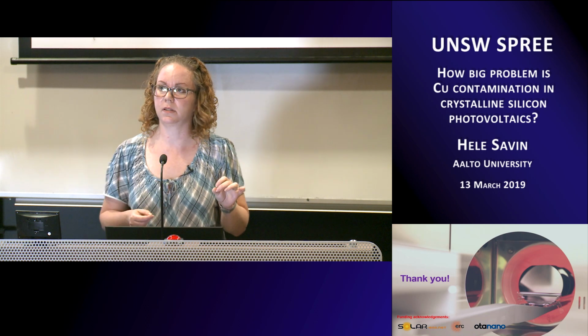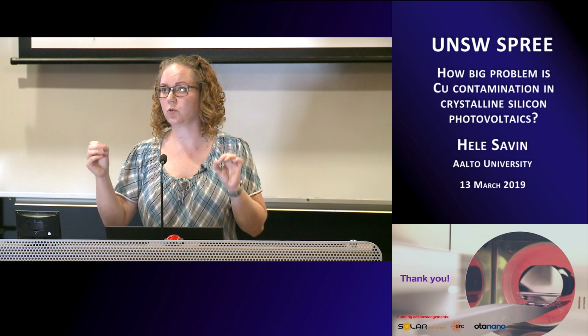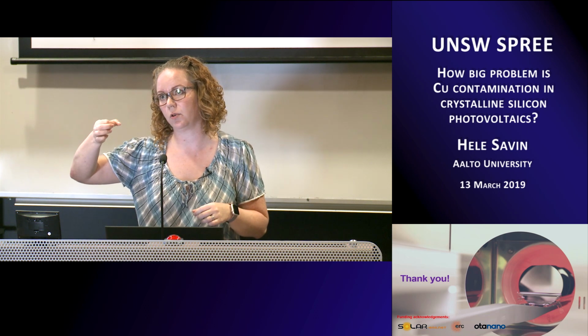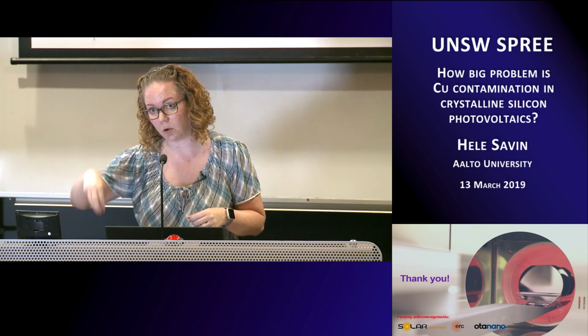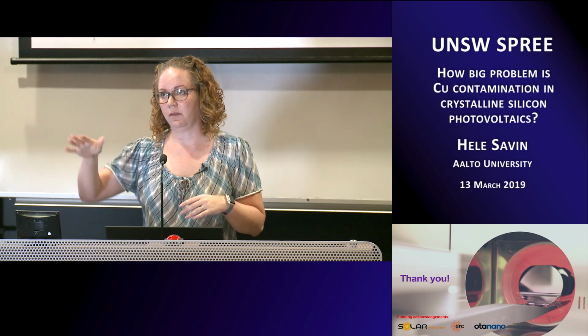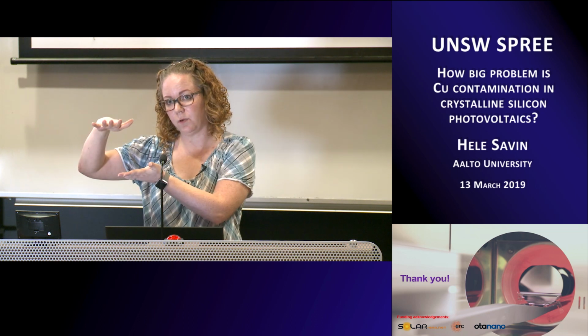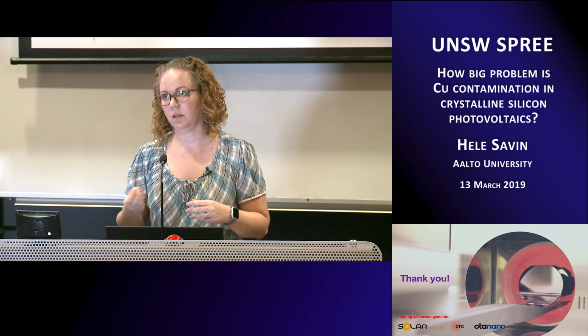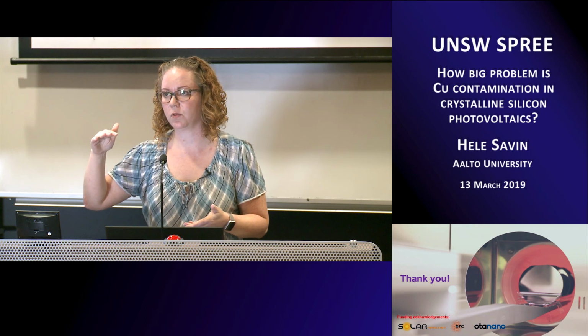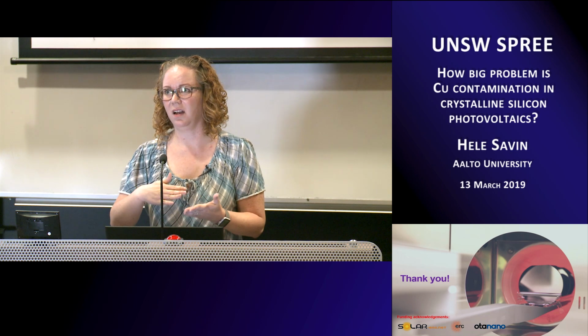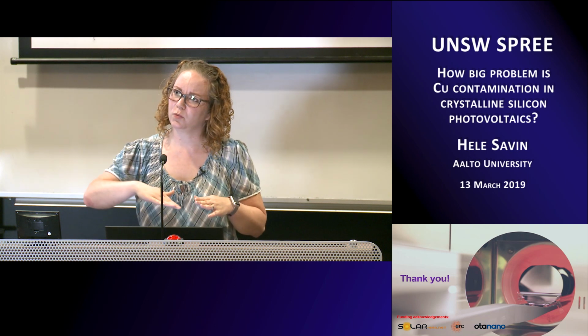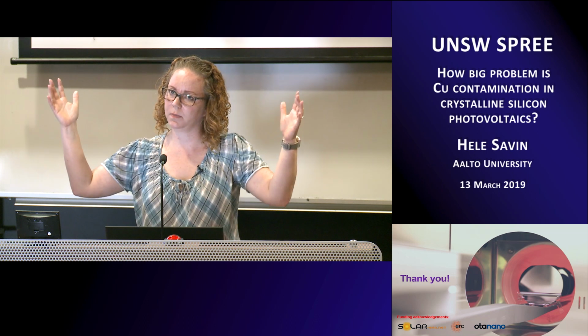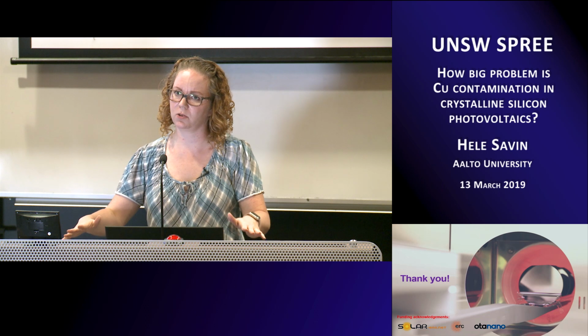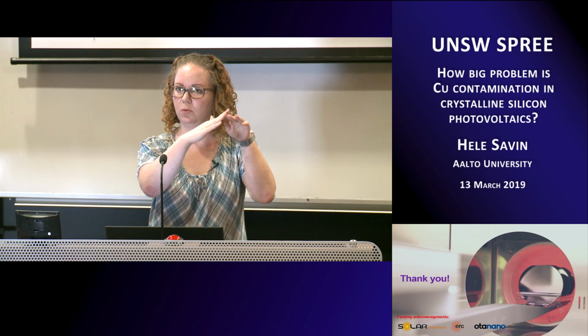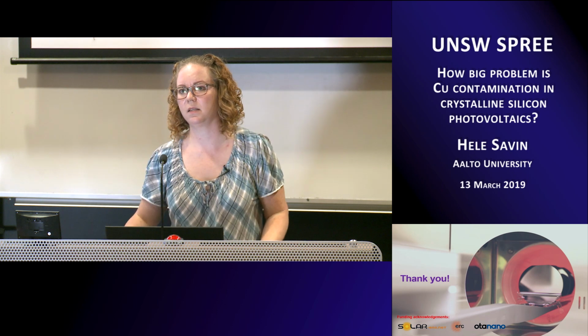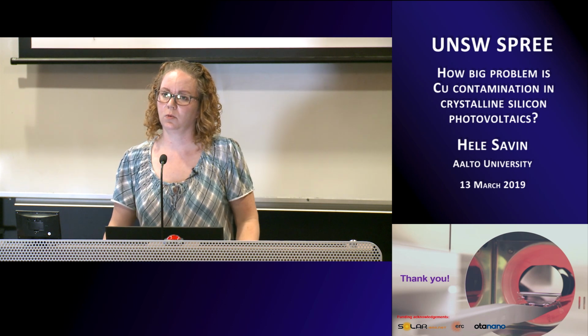The thing we have also studied in the past, which is maybe not so straightforward, is how much of this copper droplet then goes in. Can we really drive all of it in? There we have done TXRF, or chemical analysis, before and after drive-in, to know how much is going in and how much is disappearing from the surface. You have to have a special ramp rate in your furnace, because if you do this diffusion too fast, there will be some evaporation. But if you start from a really low temperature and have a really specific ramp rate, then all the copper goes quite nicely from the surface to inside.